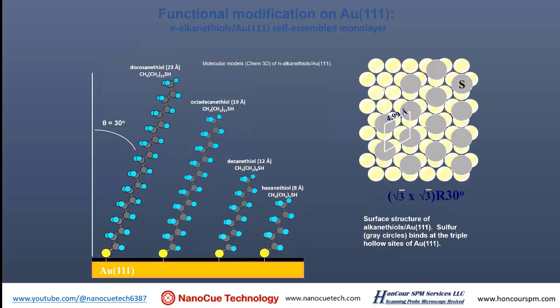So let me talk about the thiol chemistry and the reason that we use gold as a substrate. A thiol is a molecule that has a carbon chain. At the end of it, you have an SH, the thiol functional group. This SH can react strongly with the gold surface. Other precious metals probably work too. The attraction is very strong. It forms a very strong covalent type of bond.